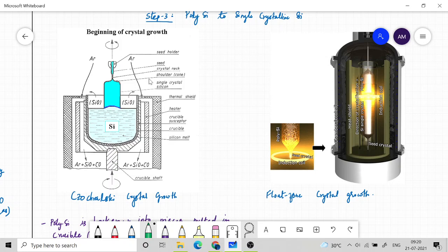So what is done is you introduce gaseous atoms into the chamber which are inert in nature, from the last group of very non-reactive elements. Argon is mostly used here. That will provide the pressure requirement, and at the same time they will not react with molten silicon.